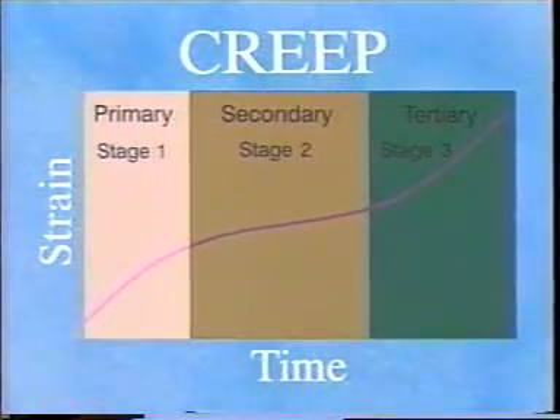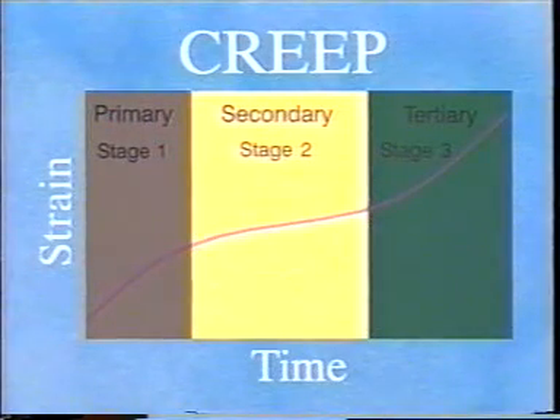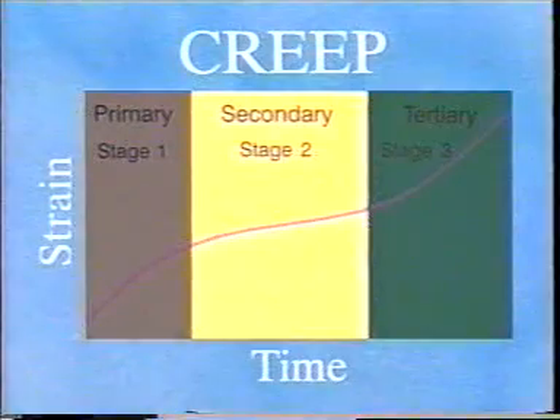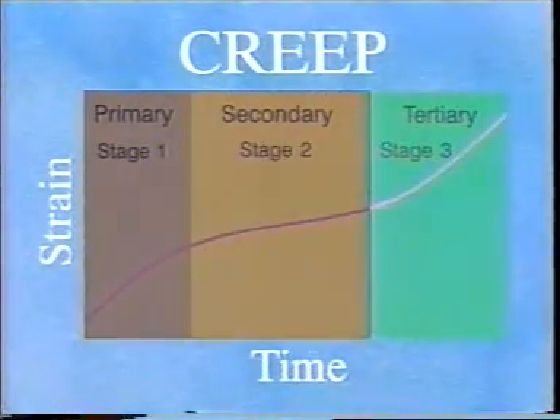There is first an elastic strain on the part or component. This is the immediate effect of the initial load. Following this initial elastic strain, there is a region of increasing plastic flow at a decreasing strain rate. This is the first stage of creep, the region called primary creep. Following the primary stage, there is a region of fairly constant strain rate. This is the second stage, the secondary or steady state creep. Finally, there is a region of drastically increased strain rate. This rapidly extends to fracture. This is the third stage or tertiary creep.